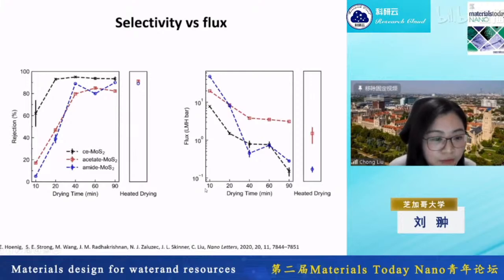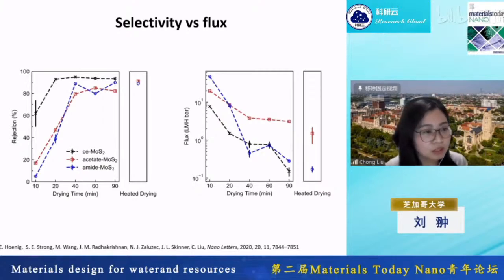So now is the time for us to really measure the performance of these membranes. Let's first look at the black curve here, which is the pristine molysulfide. As I mentioned, when the molysulfide membrane is made, it has a lot of these big water pockets and wide channels. When that's the case, these channels are percolating and you don't have a great rejection of salt, because you have a leak in the membrane.